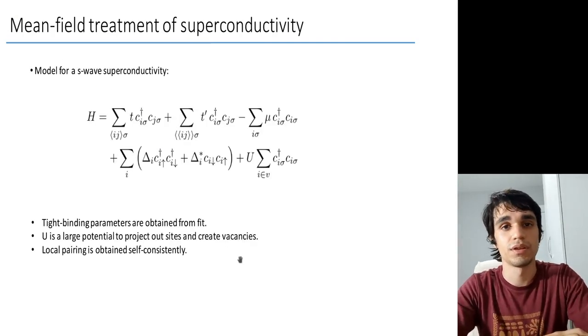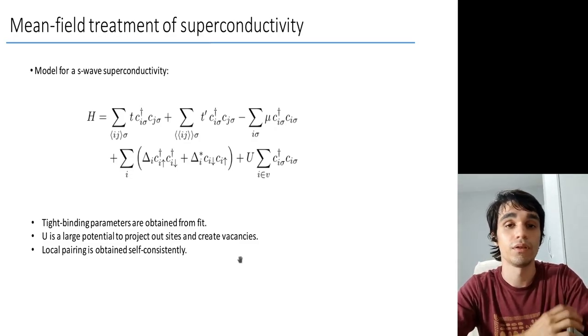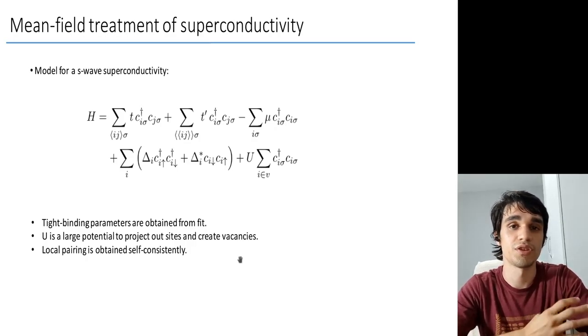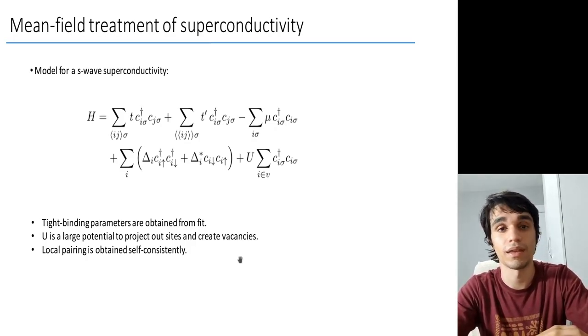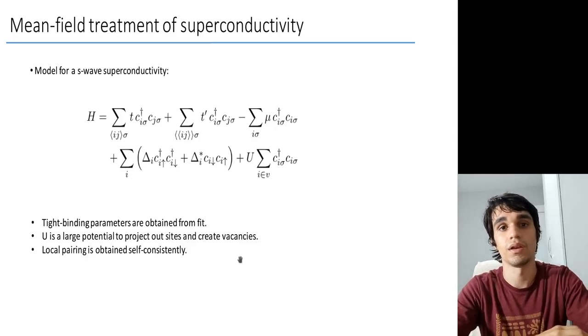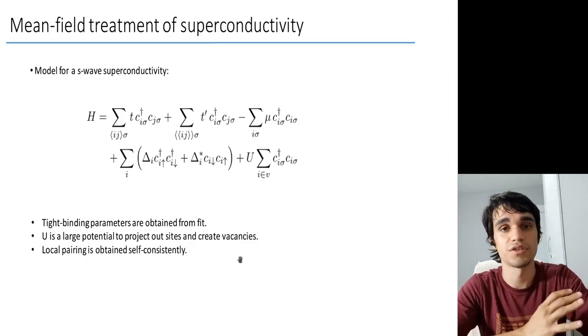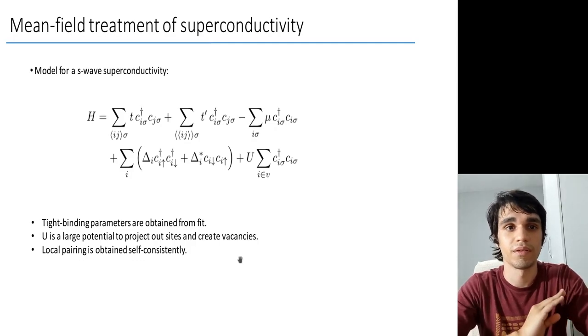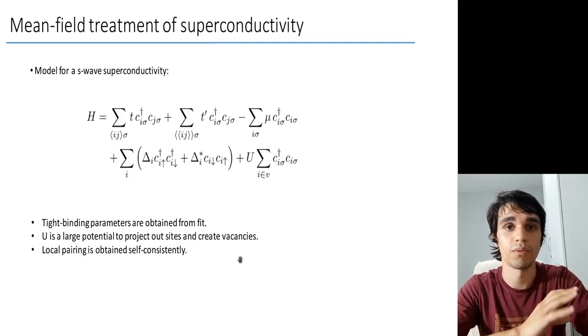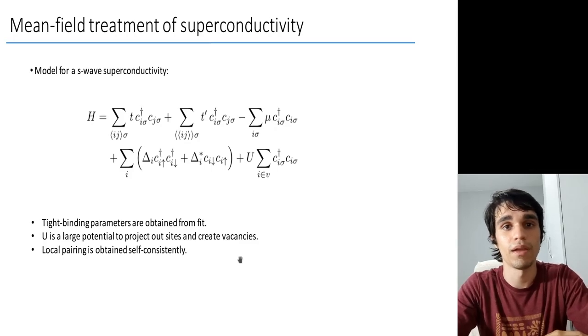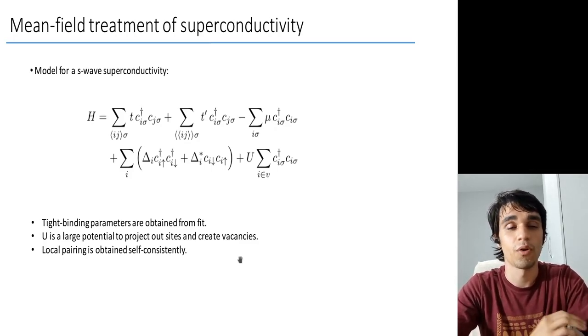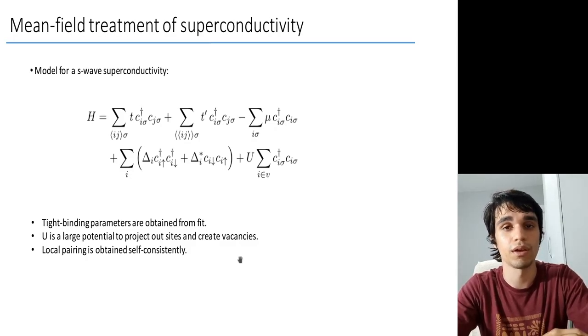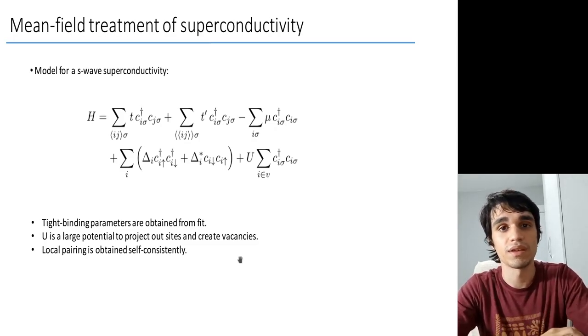So, the motivation to study superconductivity in this model is the following. The enlarged density of states should change dramatically the electronic and magnetic properties of these materials. And these changes are unclear at the moment and require further investigation. Moreover, in the realistic case, the bands are not flat. They are narrow in the range of approximately 0.5 eV. And in the meanwhile, the phonon band of holey graphene is in the range of 0.25 eV. This means that the phonon-mediated Cooper pairing is possible.